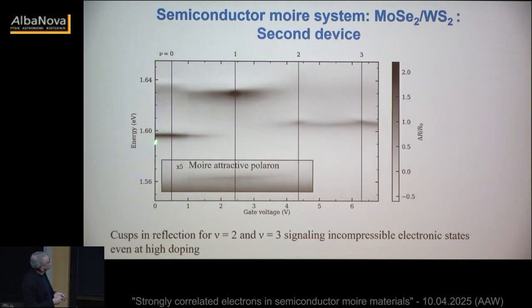So this is the spectrum. Now the spectrum is much richer. Even in charge neutrality, there are additional resonances because exciton center of mass motion is also subject to a potential. But I'm mainly interested in this low energy resonance. This is what I would call the moire attractive polaron, the counterpart of what I have shown you, in the presence of a moire potential. Okay, it's weaker. That's why we multiply by a factor of 5. But this is what we're going to deal with because we're interested in magnetic properties.